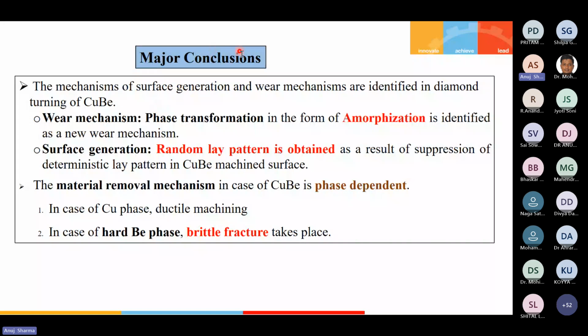So coming to the major conclusions. I tried to find out the wear mechanism and surface generation mechanism, and it was found that the dominant mechanism was phase transformation in the form of amorphization, identified as a new wear mechanism in the diamond tool when used on copper beryllium. On the workpiece surface, a random lay pattern was obtained, due to the beryllium particles that caused suppression of the deterministic lay pattern.